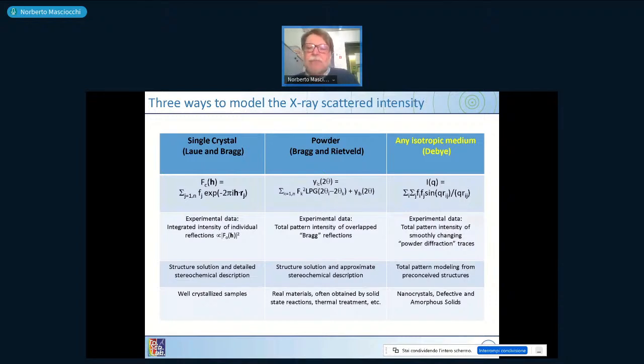Nowadays, it is possible in the most simple cases to work on a personal computer. In more complex cases, it's possible to use a server. But this means that a new technique based on a very old formula can be used. This is normally done on the so-called total pattern intensity, when you have diffuse scattering, which is scattering given by the sample, which is falling below and between the Bragg peaks.